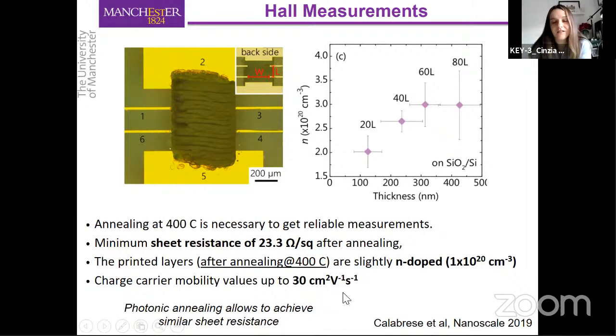And so it will not affect really too much mobility. And indeed, we found a mobility of 30 centimeters square per volt per second, which is a typical mobility that has been reported also in previous work on printed graphene films. And of course, in order to reduce the sheet resistance to 20-40 ohm per square, we had to anneal at